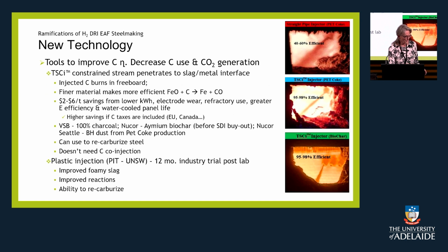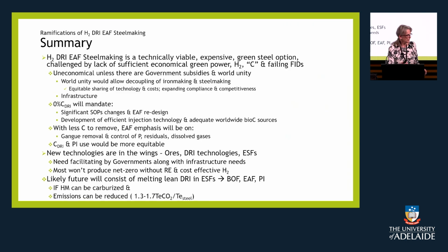New technology tools, I'm not going through all of this, but basically the Canadian companies found a way of doing supersonic injection of carbon. The finer, the better. And they've got up to 98% efficiency with the carbon and with biochar. So in summary, Hydrogen-DRI EAF steelmaking is viable, but moving forward, we need lower cost green steel, lower cost green energy, green hydrogen, and better ores that we can put through the EAF. The DRI can go through a DRI plant, no problem. It's the EAF that's the issue.